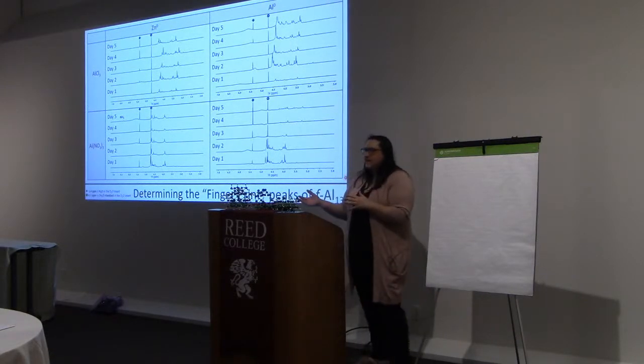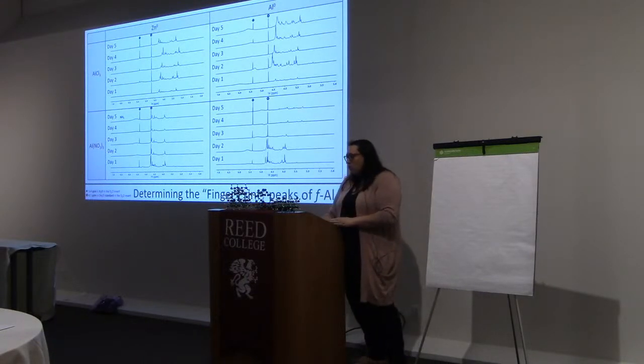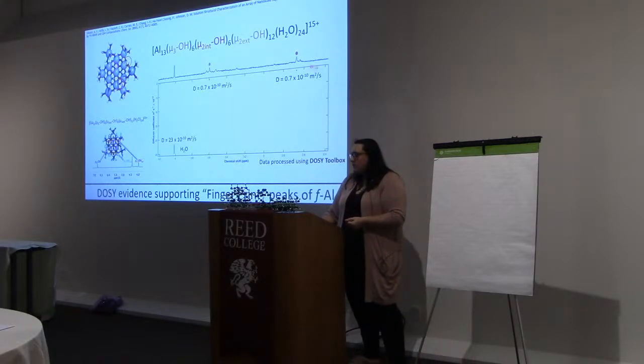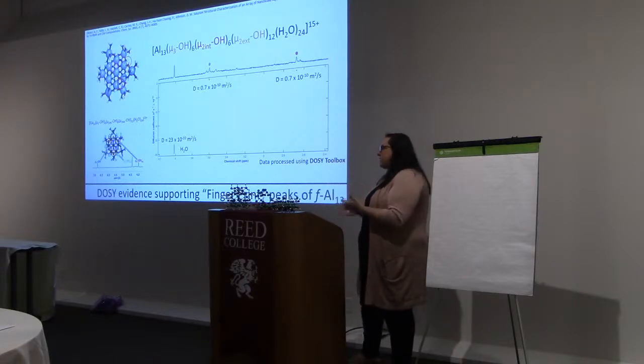There's probably dimers, trimers, tetramers, all sorts of things in there that are forming, even though what precipitates out and what has been shown to form from these solutions are those flat clusters. We took one of these that had those 2 signals very predominant, and we ran the DOSY, the diffusion ordered spectroscopy experiment. And we saw that those 2 signals correspond to something larger, diffusing slowly, so most likely our cluster.